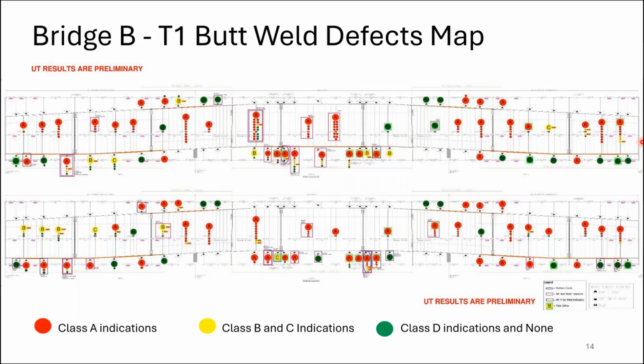So we only tested areas within the tension zone for the structure, and then only welds that had that T1 steel. The red basically indicated a class A indication. Yellow was B and C, and then no indications or a class D indication was labeled green here. And the purple boxes on this represented fillet weld indications that we were seeing in that transverse. Any red or yellow was considered a rejectable weld defect and needed to be mitigated with the permanent repair.